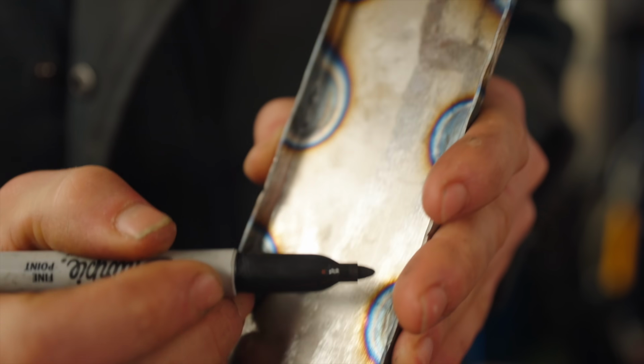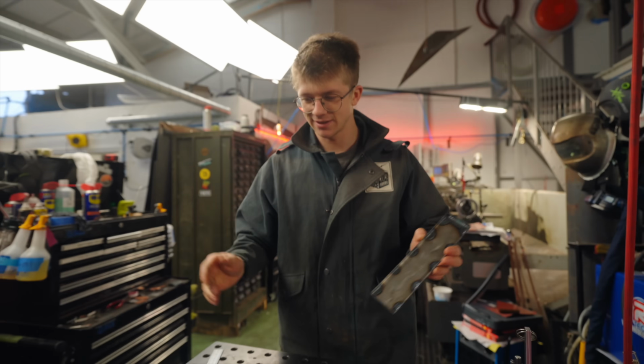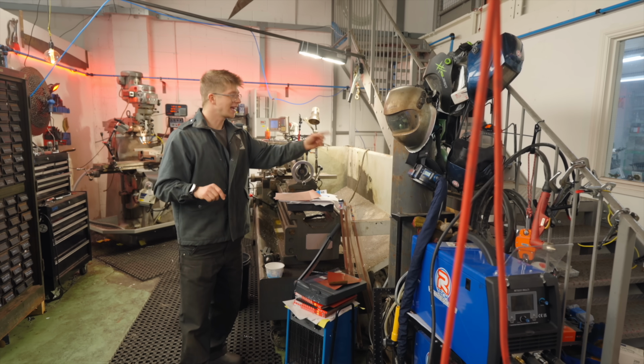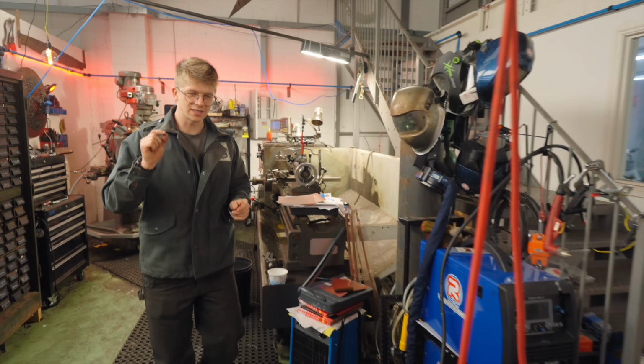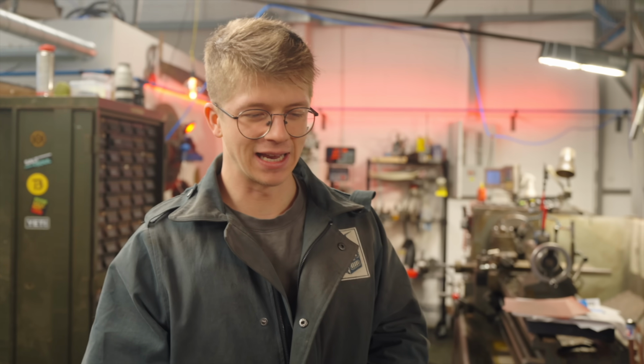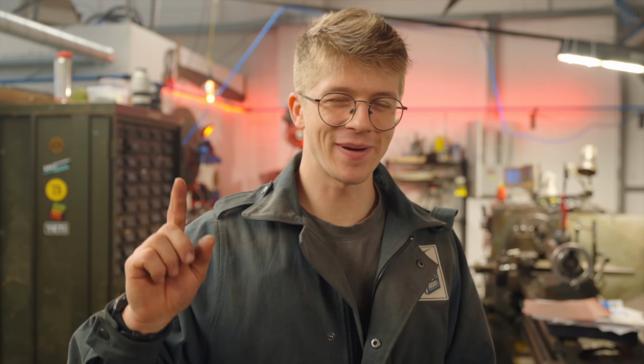Got to get rid of the inside of these welds now. First you weld it, then you get rid of the weld that you put in there. Endless. Funny thing I just noticed, I have not run out of Argon once yet since being back here after being in America. So apparently 1 bottle of Argon lasts me over 4 years.